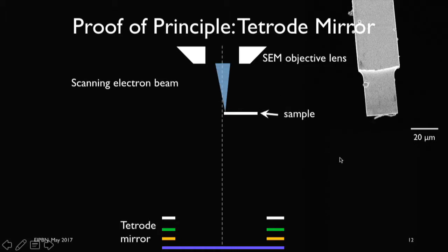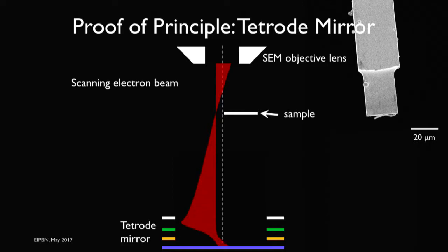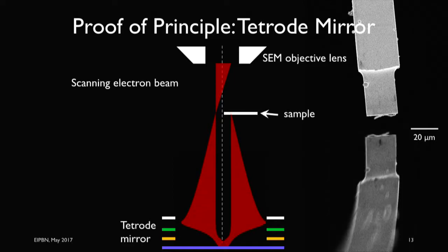So you can imagine we can scan the top surface, but at some point when we scan away from this top surface, the electron actually gets to go down, goes towards the mirror, gets reflected and refocused on the bottom surface of the sample. And just as a focused beam on the top surface was producing an image of the top surface of the sample, a focused beam on the bottom surface produces an image of the bottom surface of the sample. So in this case, you can see an image of the top surface produced simultaneously as the image of the bottom surface is produced in the same scanning of the same frame.